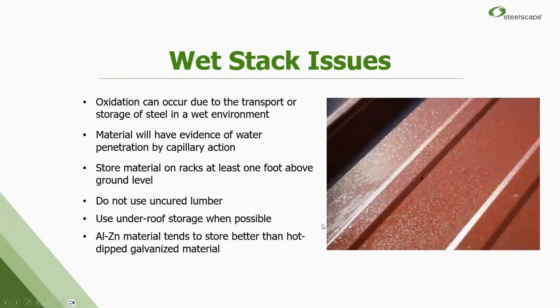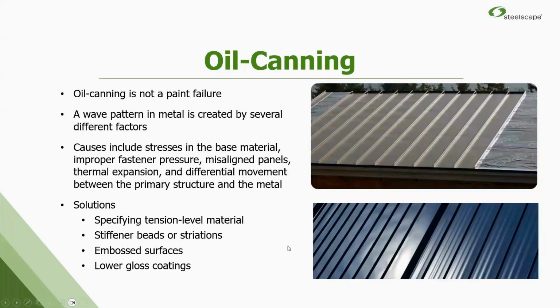Wet stack storage. This is corrosion that can occur when the panels are stacked at a job site and there's moisture present, but they can't dry out. You start getting corrosion underneath the paint prematurely. Oil canning is an installation issue, not a paint or a substrate problem, but the buckling, right? It can't lay flat or it can't expand and contract properly, so it starts to buckle. We recommend on long panels using striations, these ribs in between, to minimize that look and effect. And using the right substrate as well.